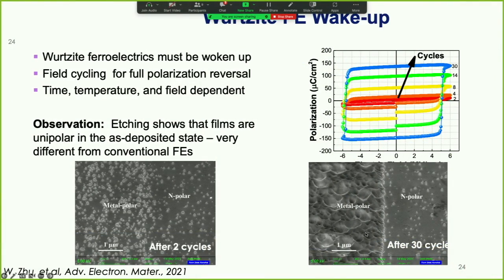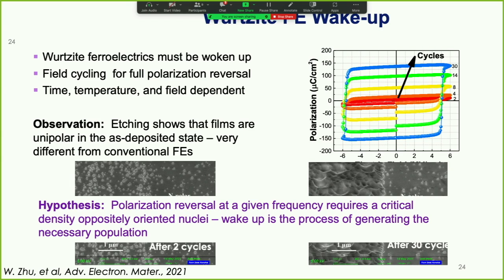We have a totally new mechanism for wake-up in these materials. We can justify that based on the fact that there is a very strong polarity dependence to the etching on all the Wurtzite structured compounds. They etch faster when they're poled in one direction than they do in another. So you can literally put it in an acid bath and say what the polarization state was. And so we hypothesized that polarization reversal requires a critical density of these oppositely oriented nuclei, and the materials grow completely poled down. So the original polarization is all associated with the aluminum nitride units in that orientation.